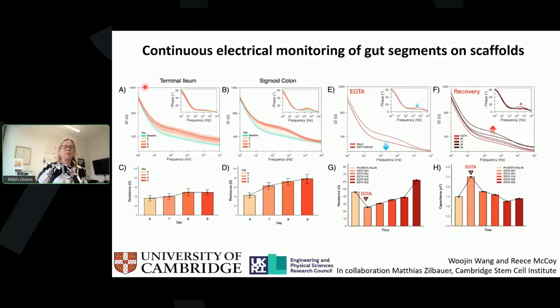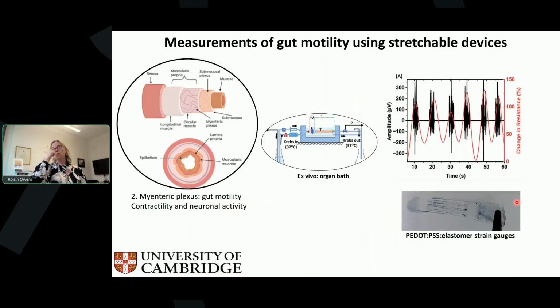So can we measure? So here we've got the terminal ileum and the sigmoid colon. We expect the terminal ileum to have a lower resistance, but we do see a shift. The sigmoid colon, we see a much more sustained shift. Our EGTA assay, so we see the decrease and then recovery. And then what we're doing now is looking at different inflammatory markers and being able to look at how we could add different microbiome samples, similar to what we've done previously with the other two.